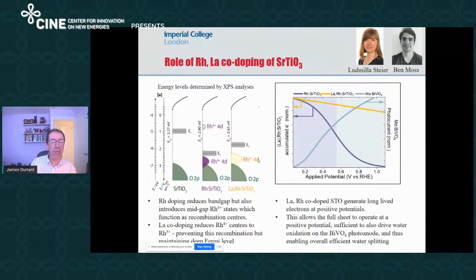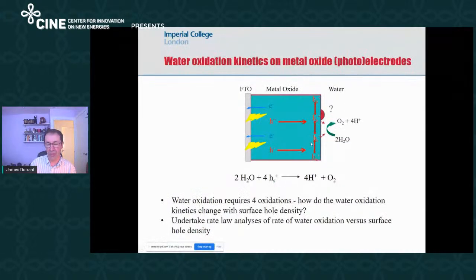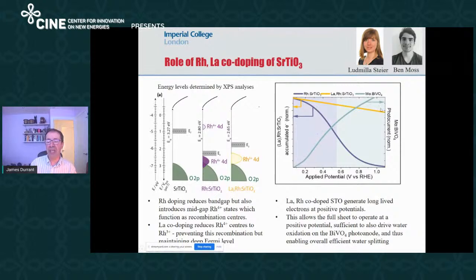The lanthanum doping takes out these rhodium 4+ states, which are the recombination centers in the system. And what that means is that we can generate long-lived electrons at positive potentials. And in particular, at positive potentials where, at the same potential, bismuth vanadate will oxidize water. And so the whole system is able to work at a positive potential to drive water oxidation. And it's also able to drive proton reduction at the same positive potential. And it's all about the ability of this lanthanum co-doping to make long-lived electrons without having to apply a potential to drive any charge separation, at least not such a strong one.